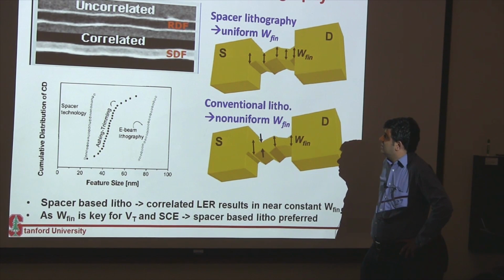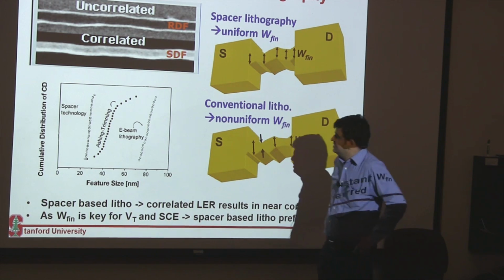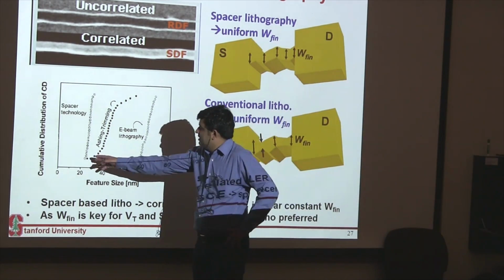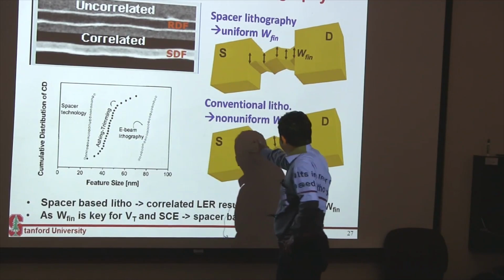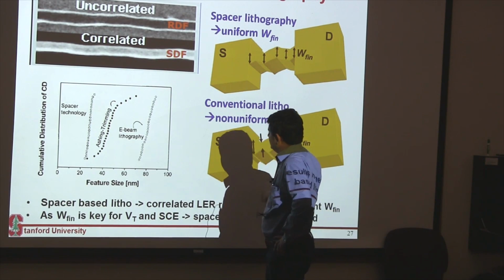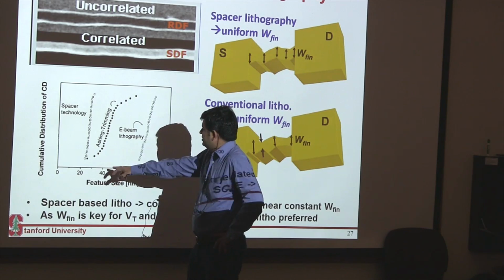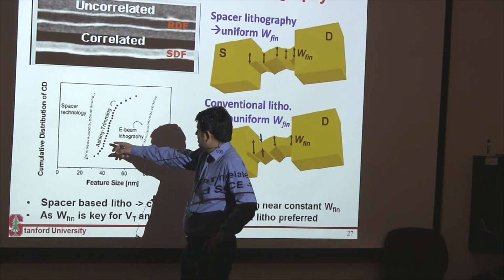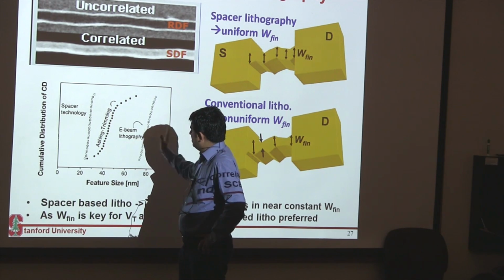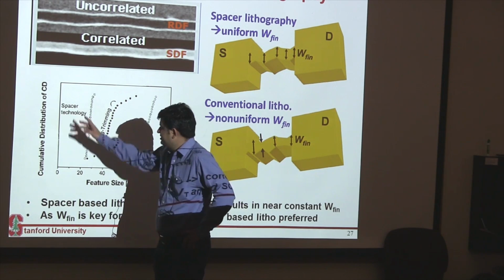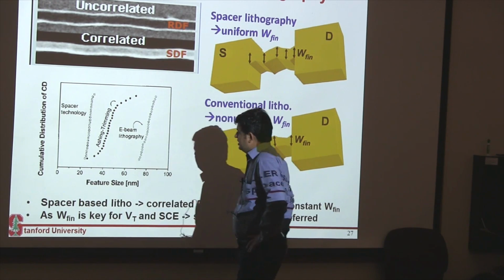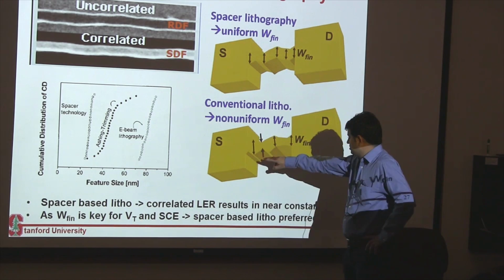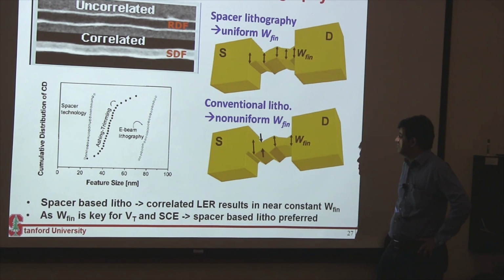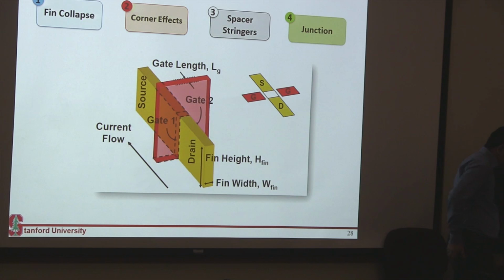So this spacer-based approach of doing lithography is really awesome for patterning these fins, because you get a constant width. So here is comparing this CD, the critical dimension, which in this case means the width. You see that if you use any other process, you get a much larger variation, versus if you use spacer lithography, you get a much tighter distribution of the width of your fin device. So this is the preferred approach that people use to pattern these fins.